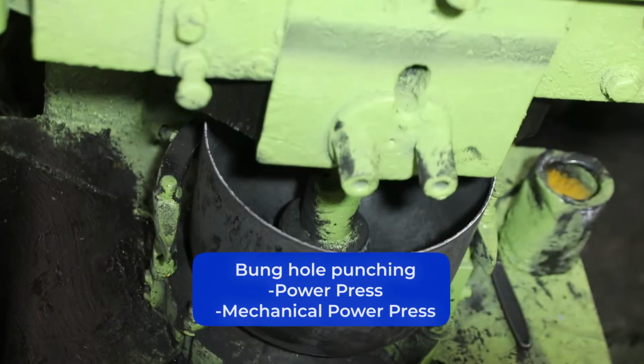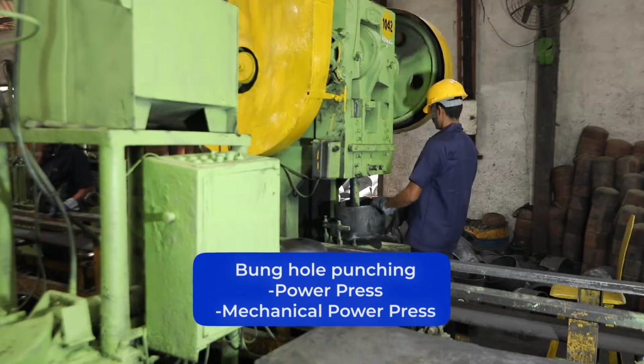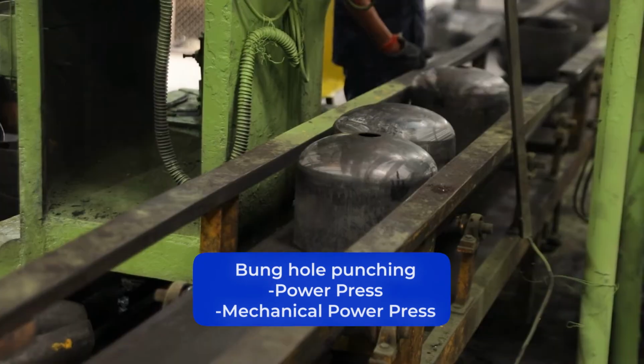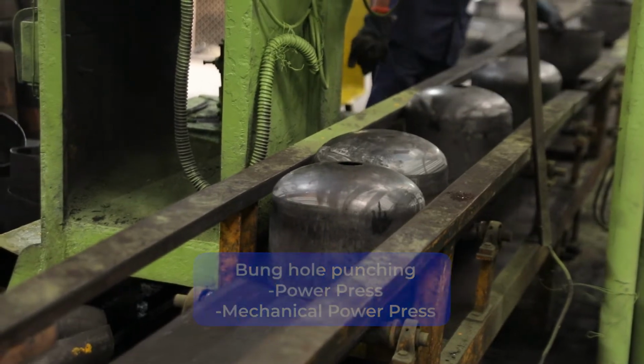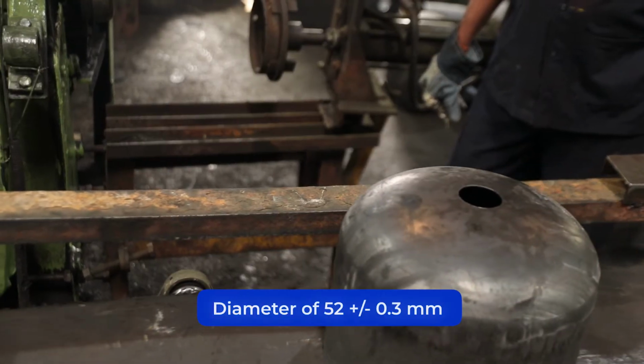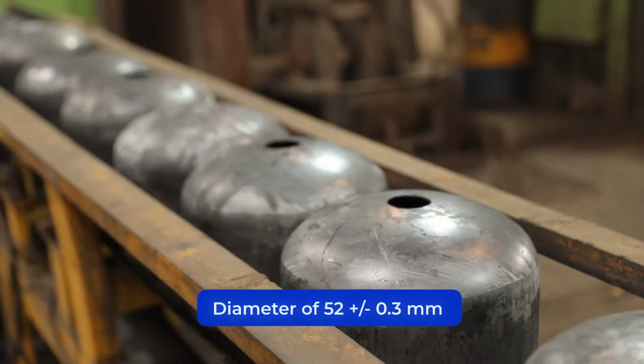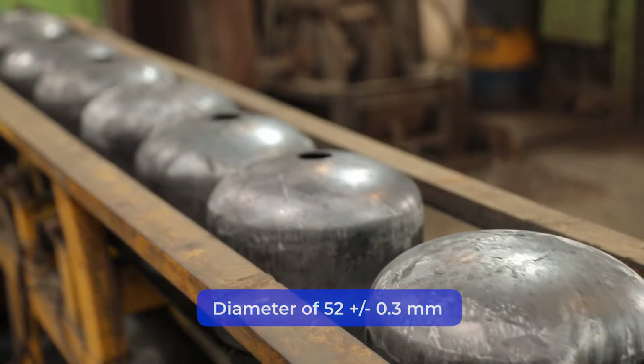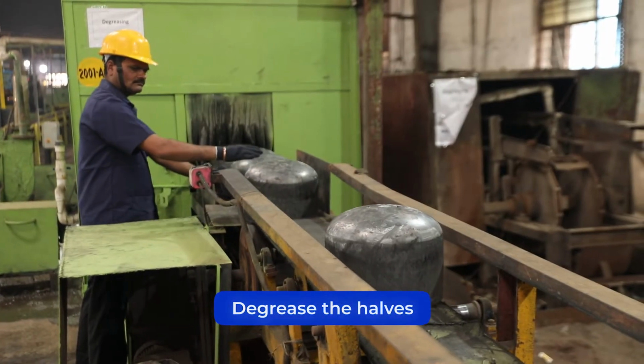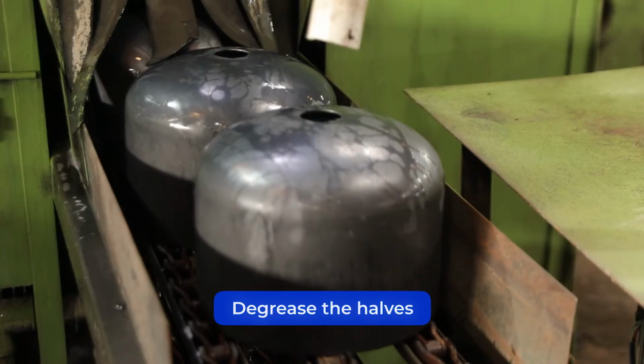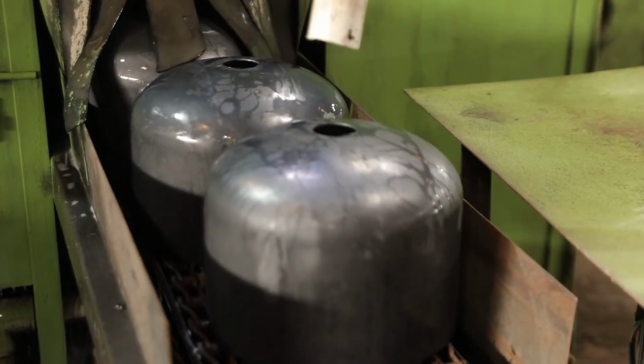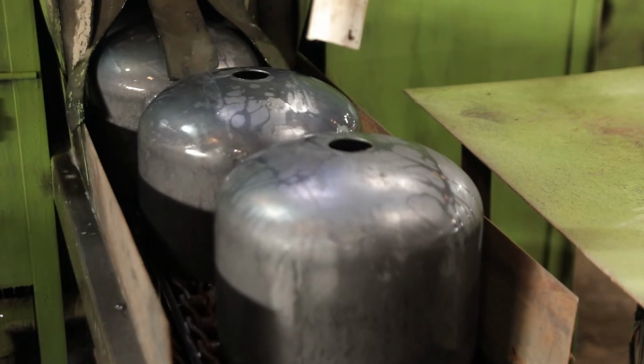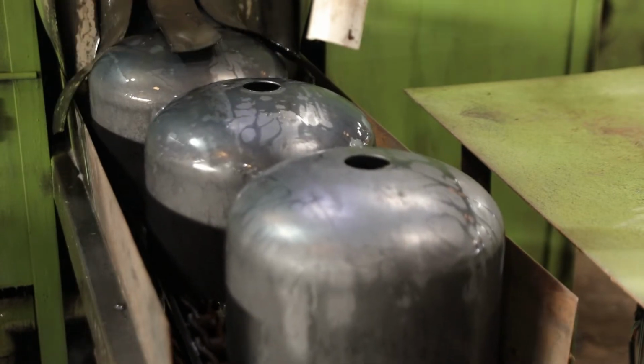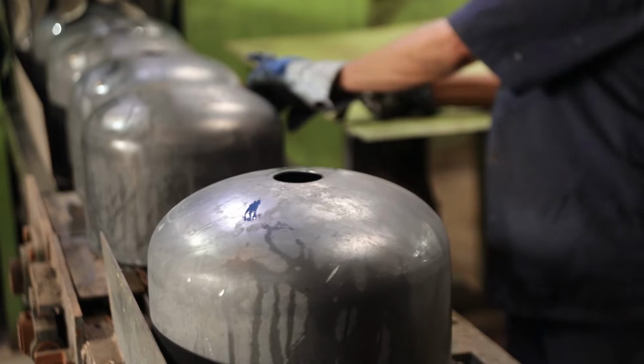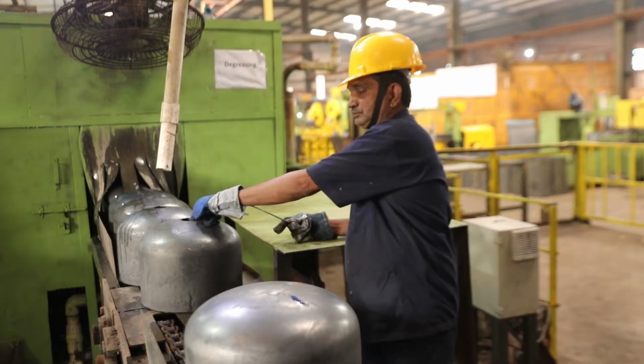After trimming, bunghole punching is made on the halves by power press or mechanical power press. Diameter of bunghole should be 52 plus minus 0.3 mm for all capacities. Clean the halves with hot water and caustic soda under a temperature of 80 degrees Celsius in a conveyorized system. This process is followed for removing oil, dust, carbon particles, etc.